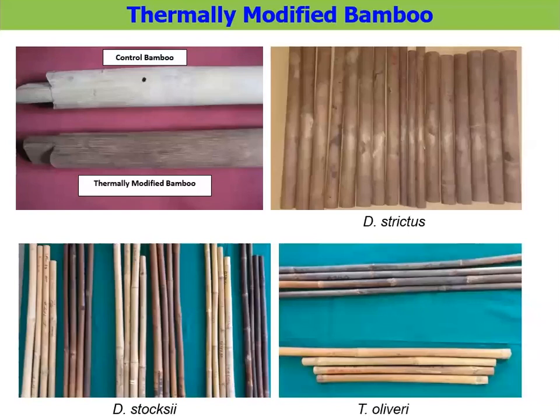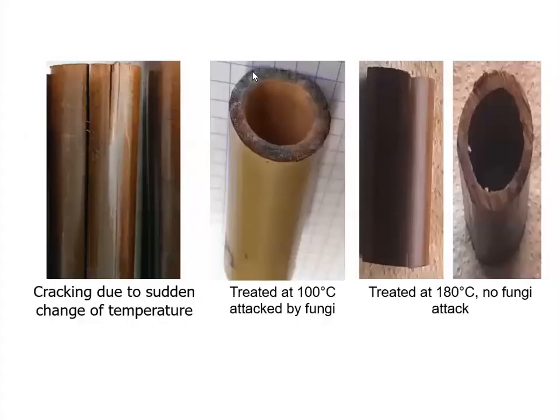The cracking is due to sudden change of temperature, so we have to do this heating in a controlled way. Only when we increase the temperature all of a sudden, cracks may develop in the bamboo. That is why we are using a vacuum oven with some kind of control over the temperature. And when bamboo is treated at 100 degrees centigrade, fungus can still attack it.